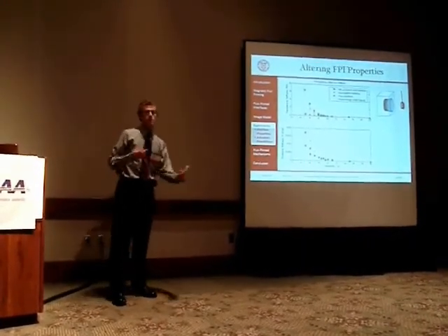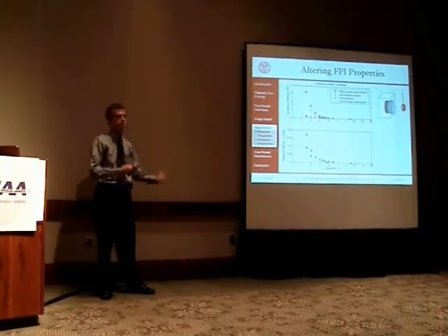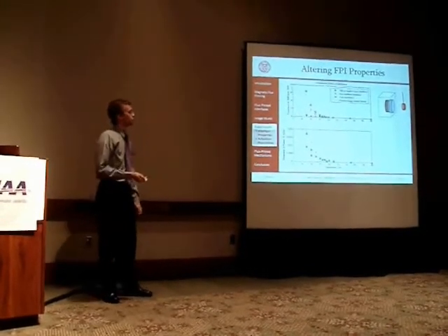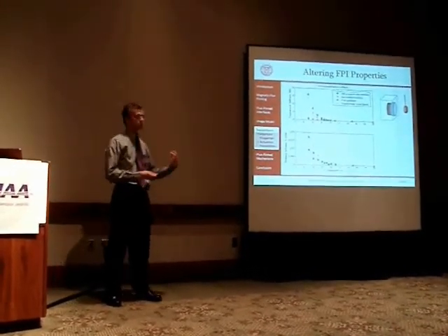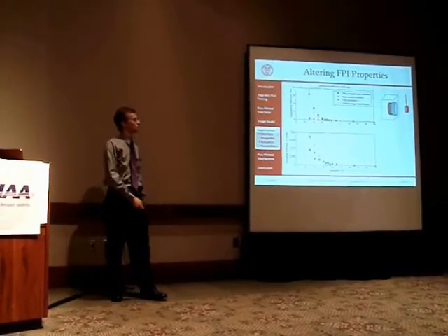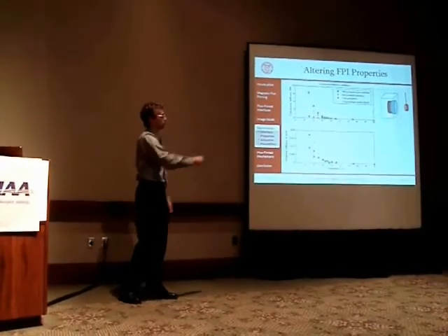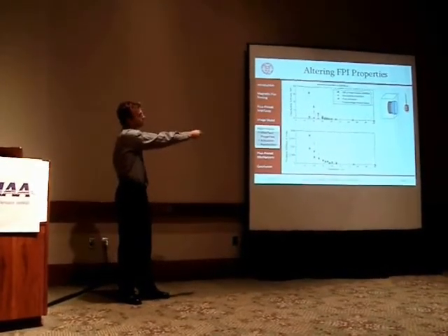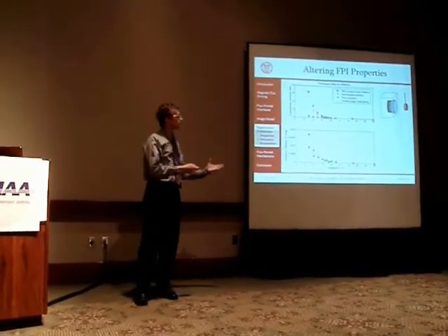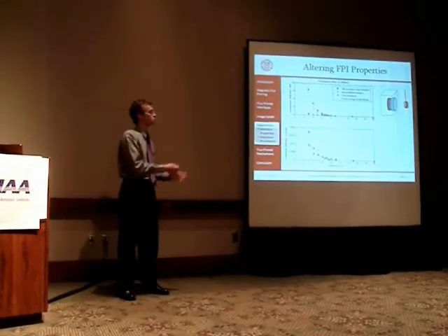Now, are there any ways that we can design this? How can we change the properties of the interface to give it certain behaviors? How can we change those properties on the fly? One way that we've been looking at is to use various metals to try to influence the flux distribution in the superconductor. So for instance, we have this pendulum with the magnet, and we have a superconductor in a liquid nitrogen tank. We can put some iron behind the superconductor before we cool it. And the iron will sort of attract the magnetic flux lines and shift the flux distribution in there.